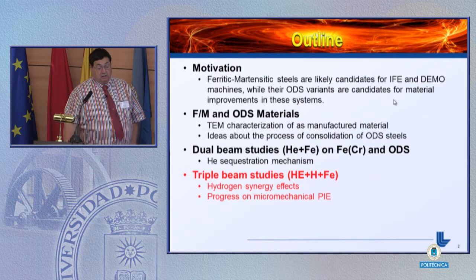Using those, we've studied the helium sequestration mechanism, which is related to the whole process of cavity formation and swelling of materials. And then we've also used triple beam studies, where we used helium, hydrogen, and iron ions. And there, I'm going to tell you a little bit about hydrogen synergistic effects and some of the progress maybe that we are making on using micromechanical techniques in the post-irradiation examination of these irradiated materials.